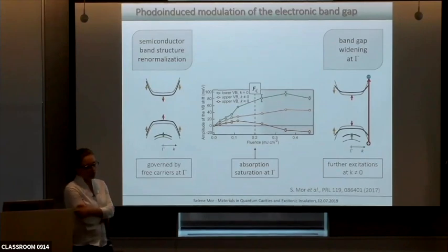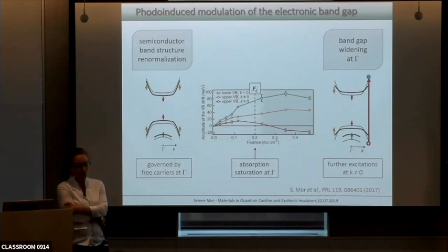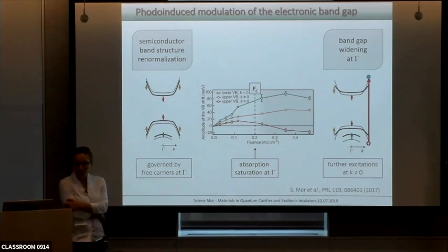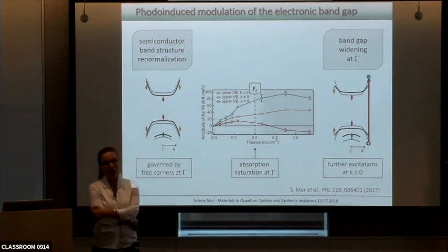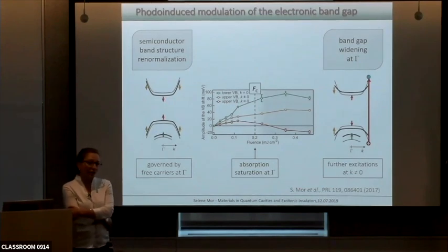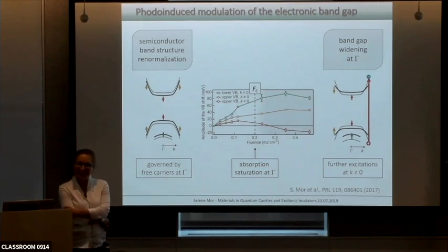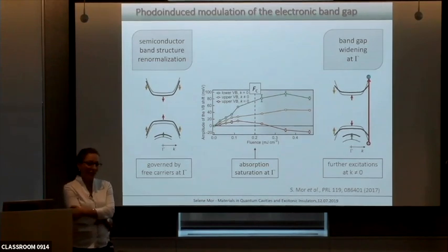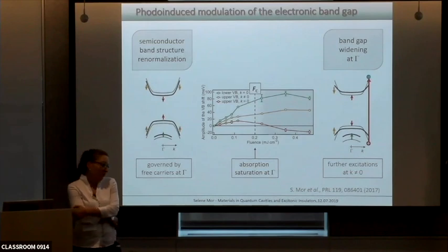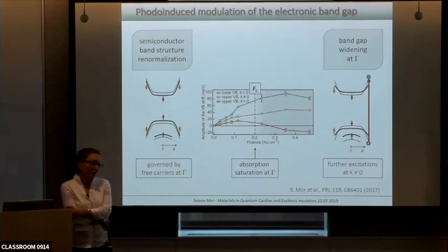So it's not here? I must say that already experimentally it's really hard with photoemission to look inside the gap. For photoemission, this is a small band gap. And already looking at the bottom of the conduction band, not even underneath, quantifying this signature is really hard, if not dangerous. And trying to extract any quasi-particle peak inside of the band gap, you have to disentangle this from a huge background, so I would not do it.